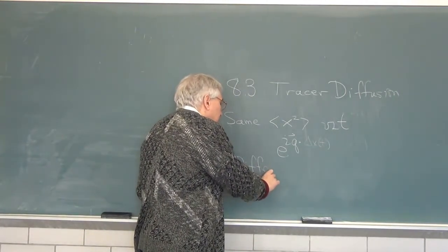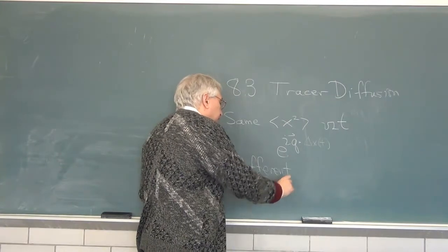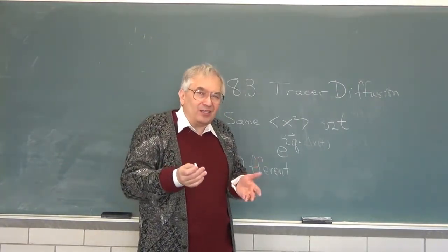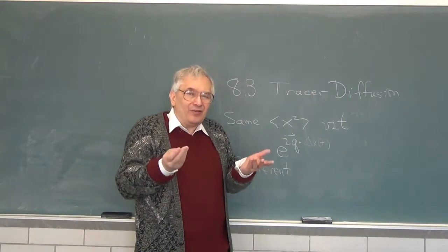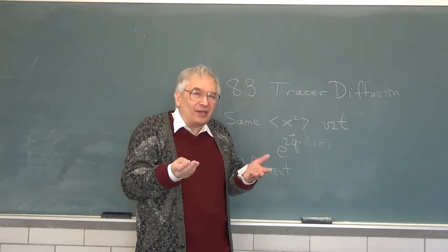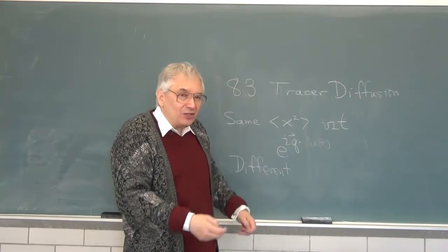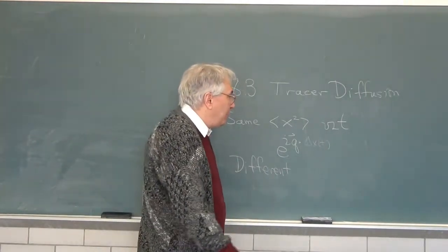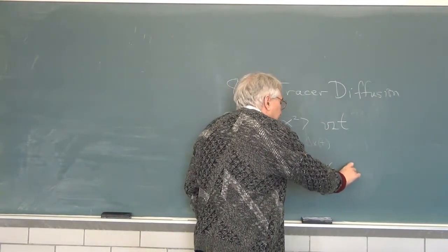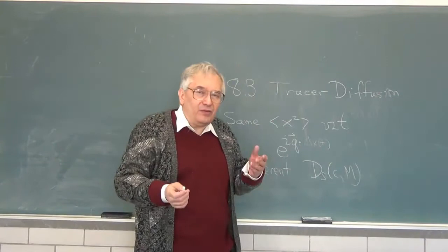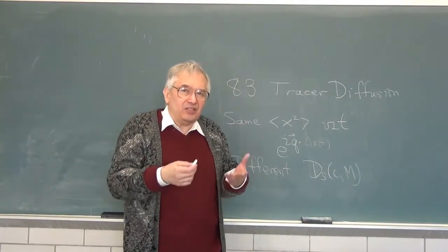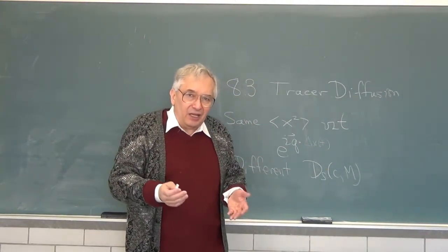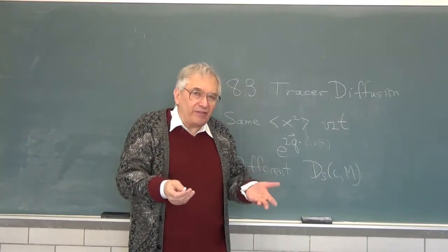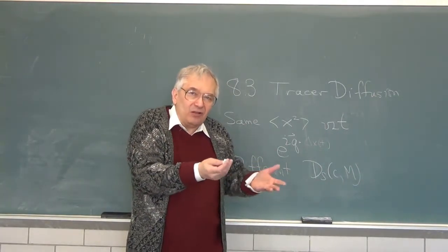There's also, however, an aspect by which tracer and self-diffusion are very different. And the aspect arises from a question. And tracer diffusion is how you get some hook on trying to answer the question. The question is as follows. If we look at self-diffusion as a function of concentration and molecular weight of the diffusing species, as we increase the polymer molecular weight, the solutions become more and more effective at slowing down the particle that's trying to move.